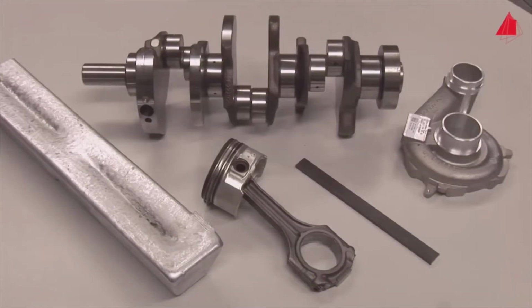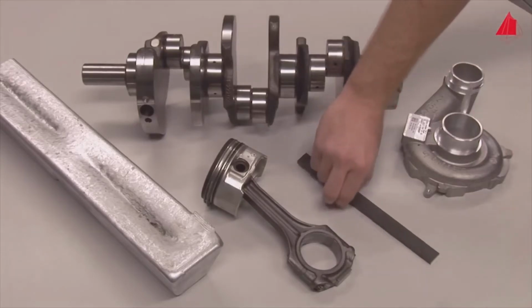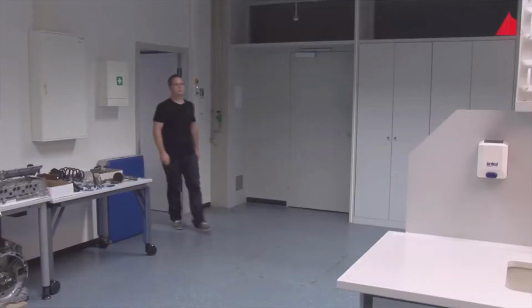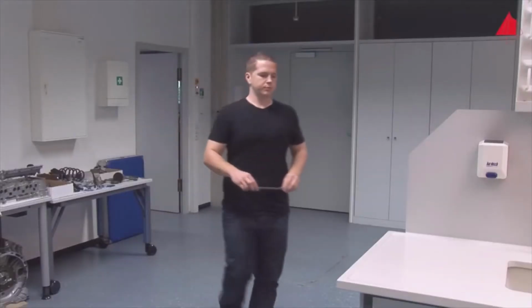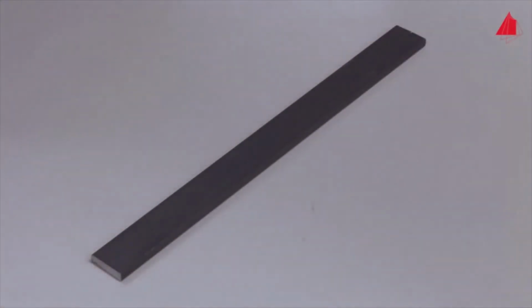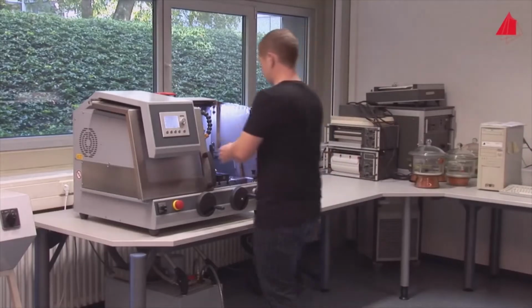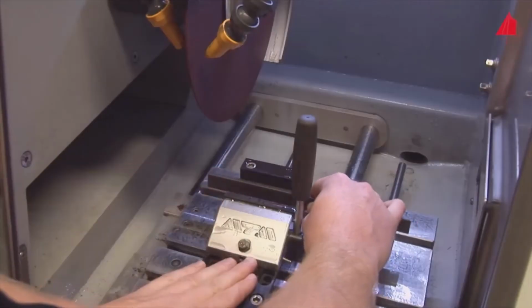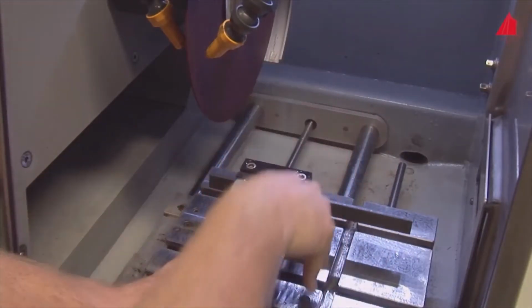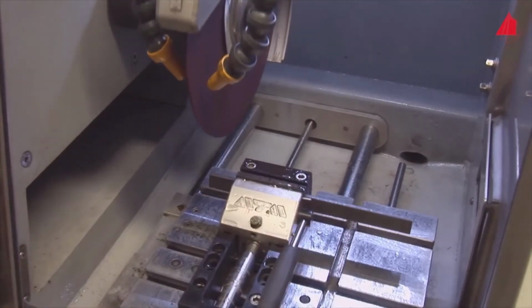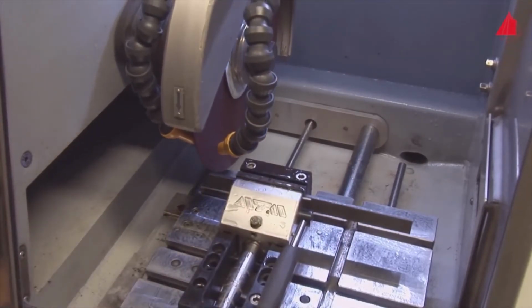As a typical example, we are going to investigate a bar made from a steel used millions of times, the plain carbon steel C45E, with 0.45% of carbon. To start with, one of our material testers defines the intended sectional plane and marks it on the bar. In this case, it's a longitudinal section. Then he takes the bar to the abrasive saw to cut out a small sample. He fixes the bar securely, prepares the machine, selects the cutting parameters, and starts the first abrasive cut.